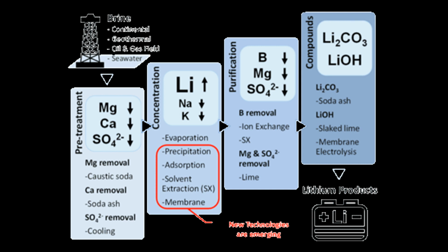Electrodialysis systems, such as our Flex EDR Selective, should be viewed primarily as concentrators and not as refining technology. This is because today's monovalent EDR systems cannot separate sodium from lithium, and although monovalent electrodialysis may separate monovalent ions from divalent ions, the separation is less effective than chemical methods in the case of lithium, resulting in higher yield losses.